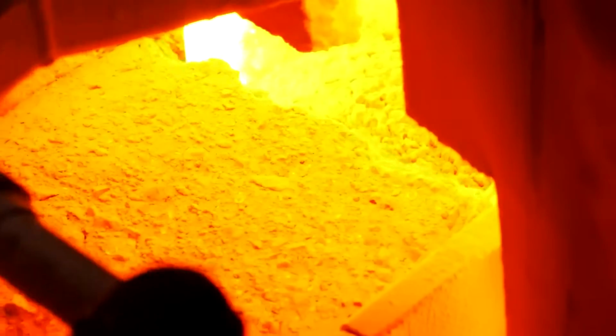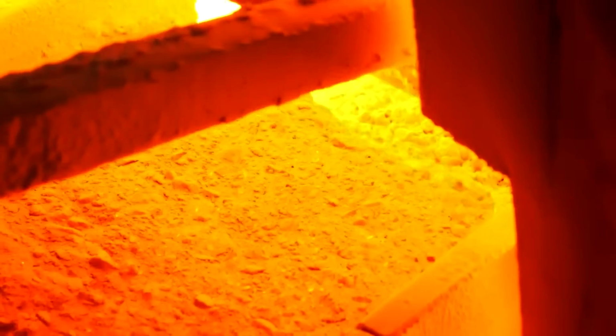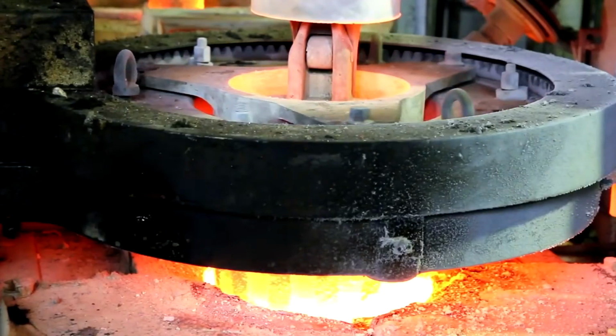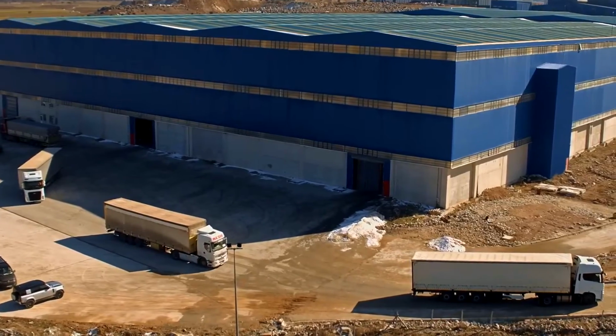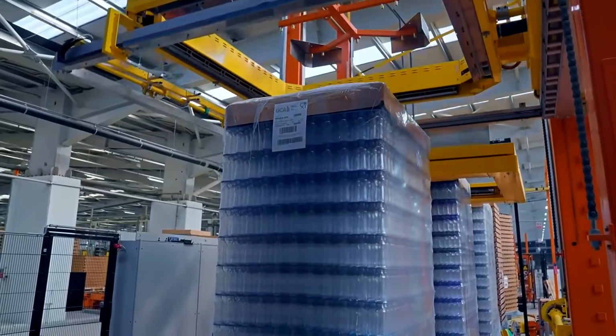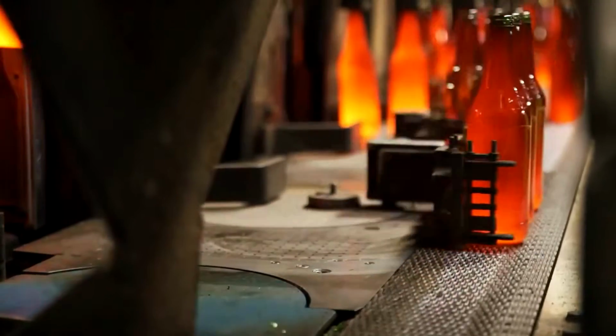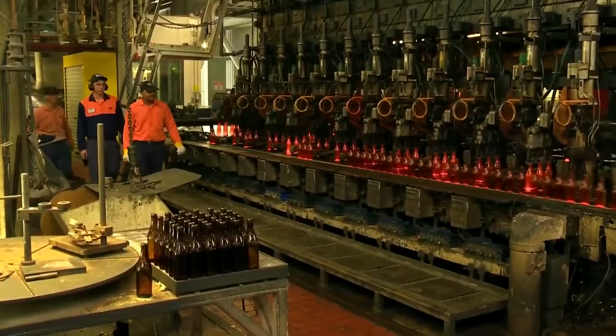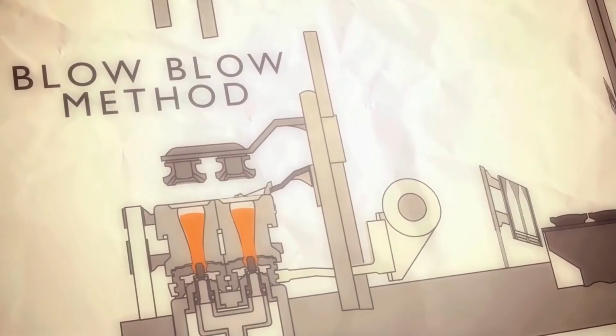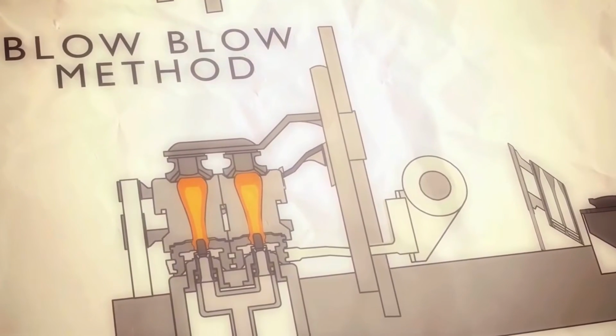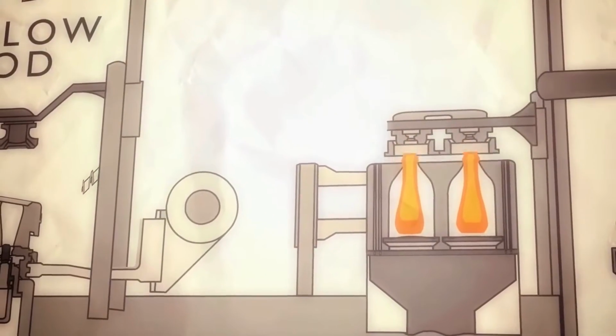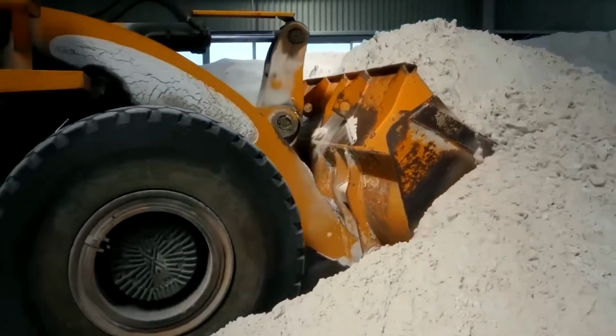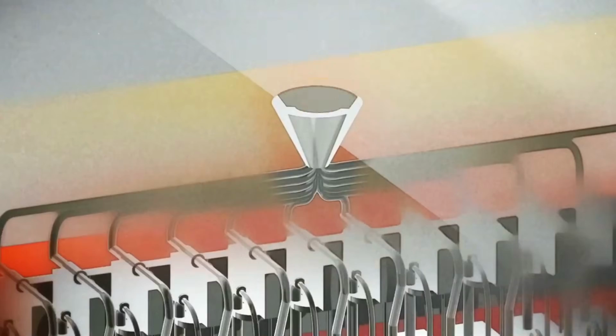The forming process ignites as gobs of molten glass are dropped into an initial blank mold. These gobs are sheared from a continuous stream of liquid glass, glowing at around 1,011 degrees Celsius, and possess the perfect viscosity for smooth and consistent shaping. Inside this preliminary mold, a jet of compressed air is blown from above, pushing the hot glass outward to conform to the mold's walls. This action creates the initial shape, a hollow bubble-like structure known as a parison, which already has a narrow neck. Still glowing with intense heat, the glass is gently transferred to the final mold, positioned just a few inches away on the same production line.